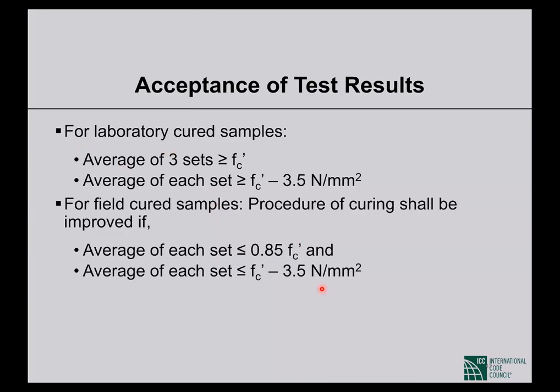And this is another quite frequently asked question: if the test result is less than the design strength, should we demolish the structure? What is the acceptance criteria? For samples which are cured in the lab, you have to understand, you collect the cylinder in the field and send it to the lab. That will be cured in a tub in the laboratory, completely immersed, so fully cured. So if the samples are cured in the lab, then the average of 3 sets must be greater than the fc prime.